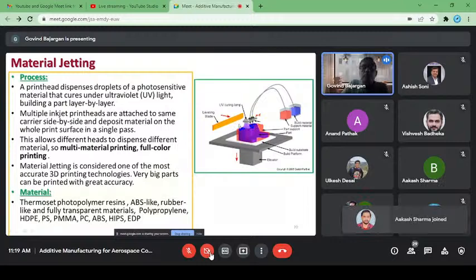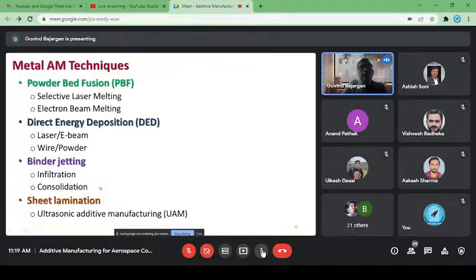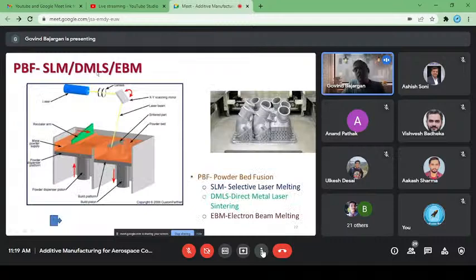In metal 3D printing, we have powder bed fusion, direct energy deposition, binder jetting, and sheet lamination. In powder bed fusion, which is known by the names selective laser melting, DMLS, or electron beam melting, metallic powder is laid on the print platform, and the laser scans as per the 2D drawing, and the build platform moves down. This is how powder bed fusion builds the metal part.